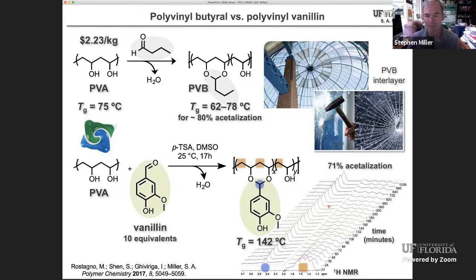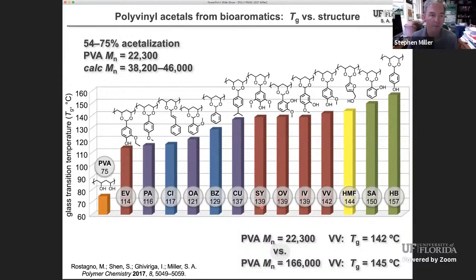This is the attachment shown in a closed NMR tube. So it doesn't really have to be driven. You can get up to over 70% acetalization in a closed system here with 10 equivalents of vanillin in the course of 17 hours or so. So its synthesis is not particularly challenging. You can get a reasonable amount of acetalization, and you do increase the glass transition considerably, all the way from about 75 to 142 degrees, which of course would widen its thermal application envelope.